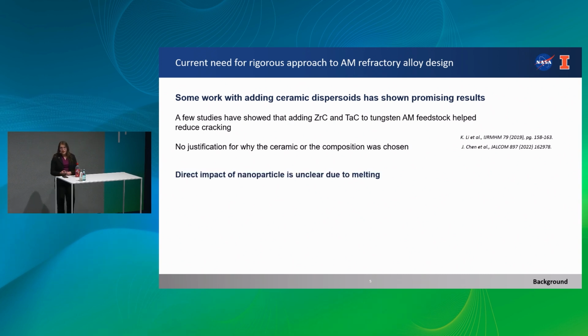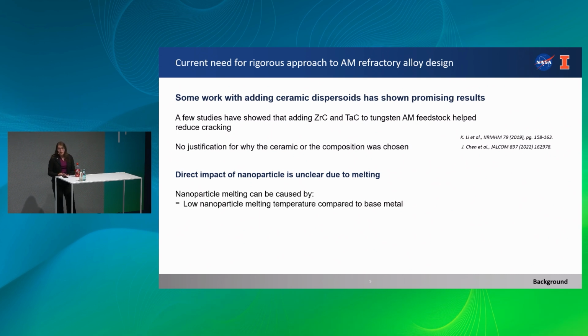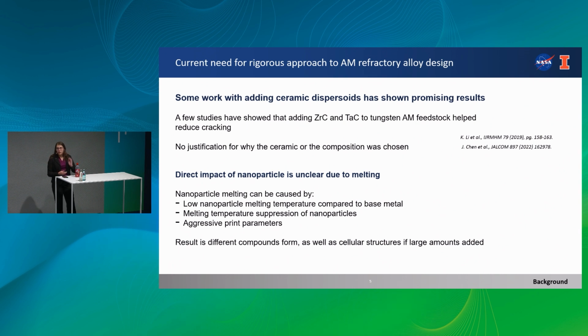In these studies, the direct impact of the nanoparticle was particularly unclear because the nanoparticle was actually melted in both cases, and this can be caused by a low nanoparticle melting temperature compared to the base metal. Because nanoparticles are so small, you can get melting temperature suppression, and a lot of times people use overly aggressive print parameters to help get really high densities. But then what ends up happening is that you end up melting even the nanoparticles that have a higher melting temperature than your refractory metal.